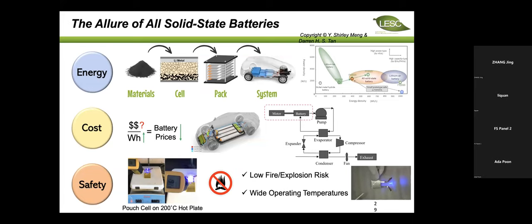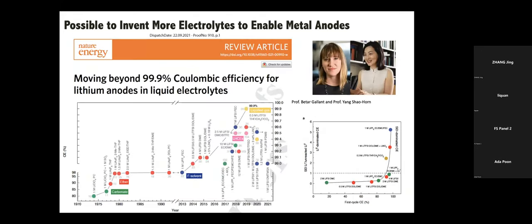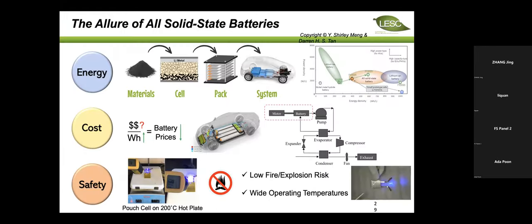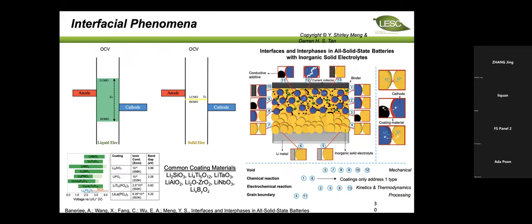Now, the ultimate dream for all of us is, of course, to move forward to solid state, right? Because even with 99.9% efficiency after 1,000 cycles, the safety of lithium metal batteries still cannot be figured out if we're using liquid electrolyte. So we want to do solid state, but it's not easy, right? Because solid state is actually much more complicated, in my opinion. When we look at the sulfide-based solid state batteries, because the solid electrolyte is powder, right? Of course, in the metallic lithium part, you have a complexity because any void you create is an additional